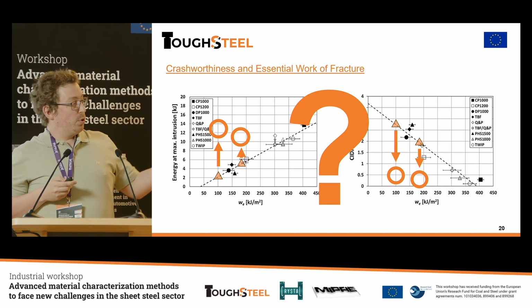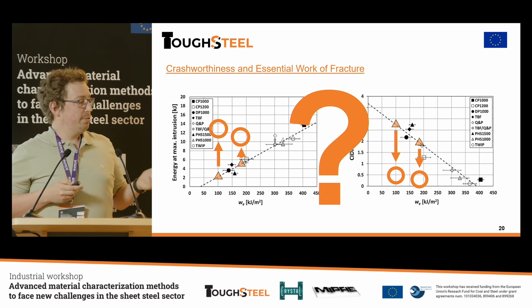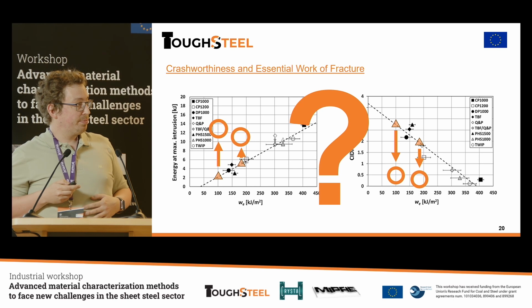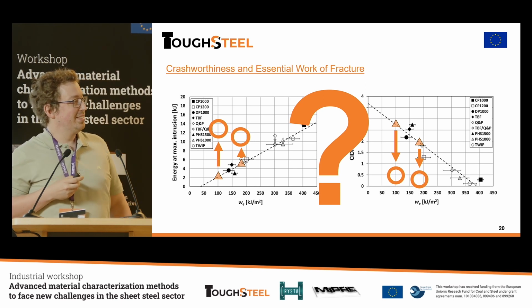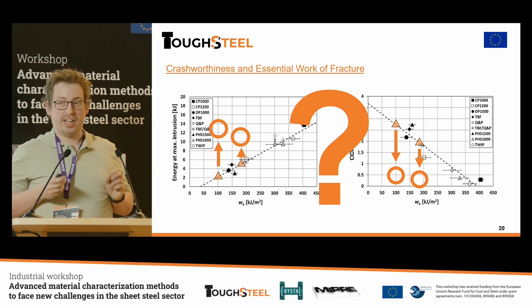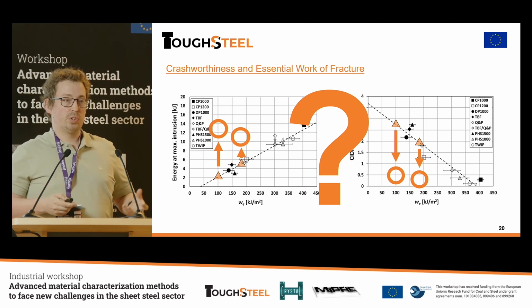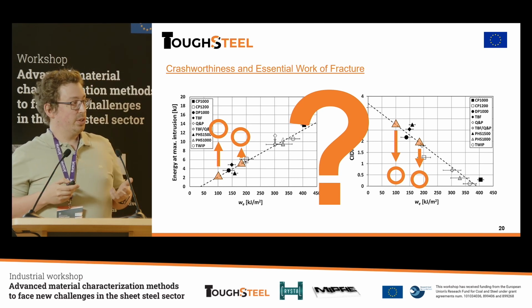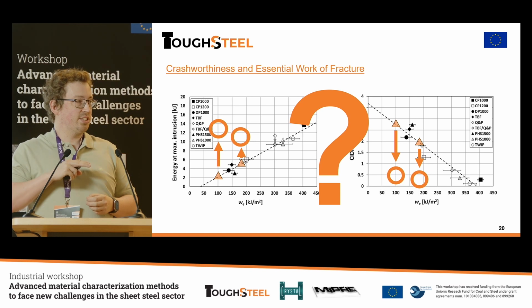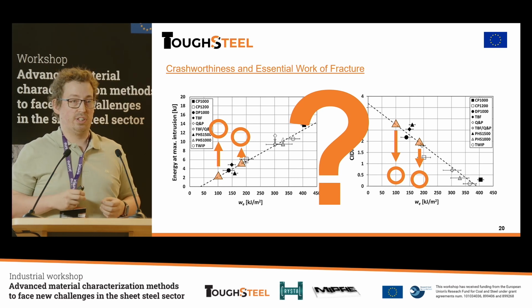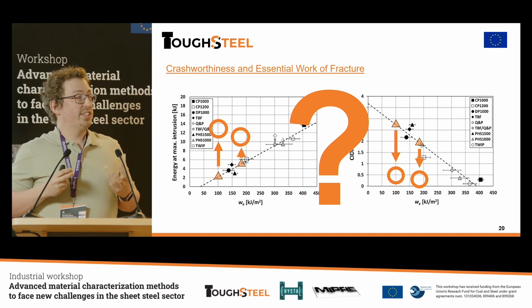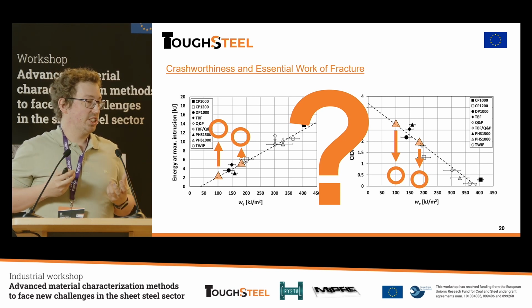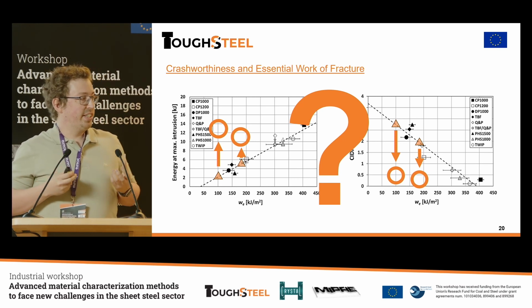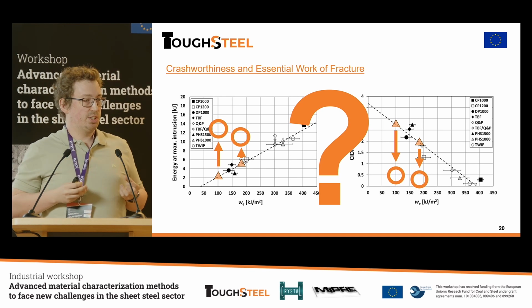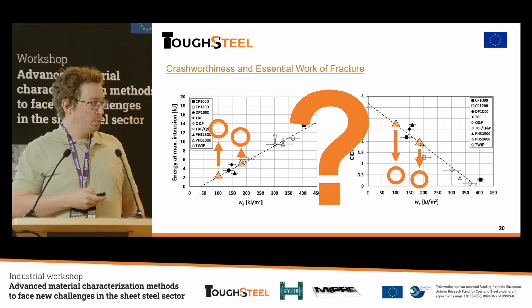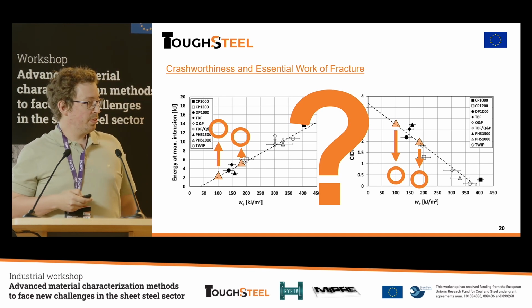But furthermore, of course, it's been shown by Frómeta and Golling here as well that essential work of fracture is highly strain rate dependent. So we are almost always crushing these boxes at 20 meters per second. So locally, the strain rates are over 1,000 in these crash boxes. So we have incredibly high strain rates. And essential work of fracture increases with strain rate, as has been published before.